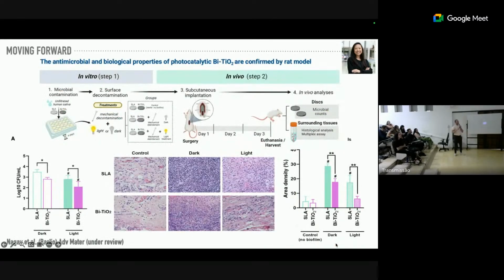We also ran some in vivo experiments using in vivo infection. For this, we use a microbial contamination using the in vitro model that I'm going to show later. And these discs were implanted in the dorsal of the rats. And then after light exposure and during 3 days, the rats were sacrificed, and we counted the number of bacterial cells on this infected tissue. As you can see, for the surfaces that were light exposed, we observed a reduction in terms of contamination, especially for the bismuth that has a photocatalytic effect under visible light.